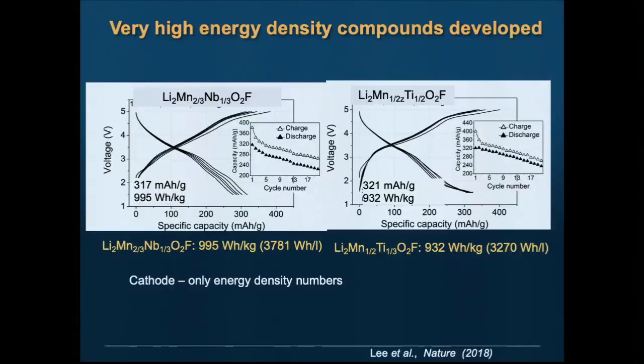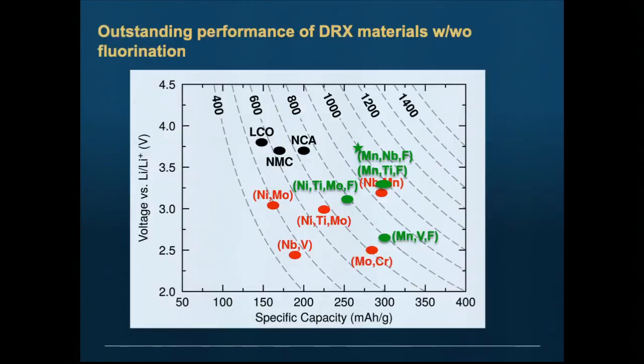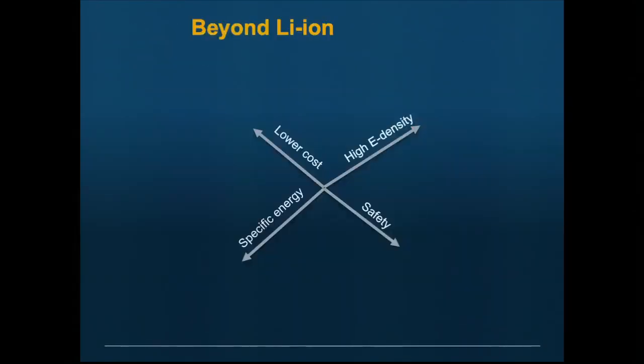We've been able to go to really high energy contents, almost approaching 1,000 watt hours per kilogram, which in contrast, today's best cathodes are about 650 to 700 watt hours per kilogram. And we can do it with fairly cheap elements like manganese and titanium. This one is manganese and niobium, which is not the greatest. It's in a similar situation to cobalt, but this one is actually very good. Okay, let me skip that. So we've unlocked the periodic table.